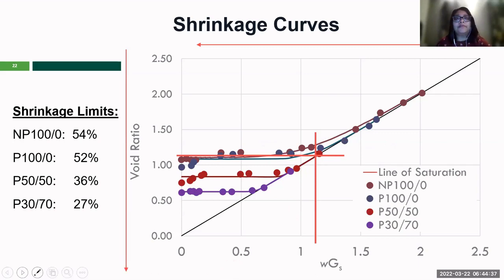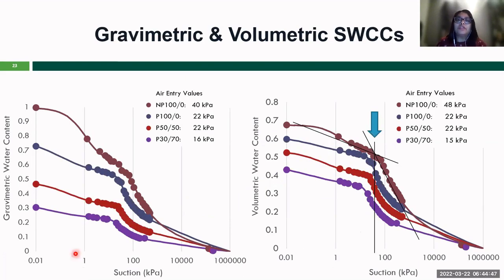Okay, now we will move on to the next data points here, with the gravimetric and the volumetric soil water characteristic curve. So if you look into those data points, water content with respect to the suction, and 4 different samples that we have tested, again, we are presenting in 2 different types of water content, gravimetric and volumetric. And because we have tested only up to 500 kPa suction level for this material, there is no point of looking into the high suction level, because we already found out what is the range we need to work for these materials.